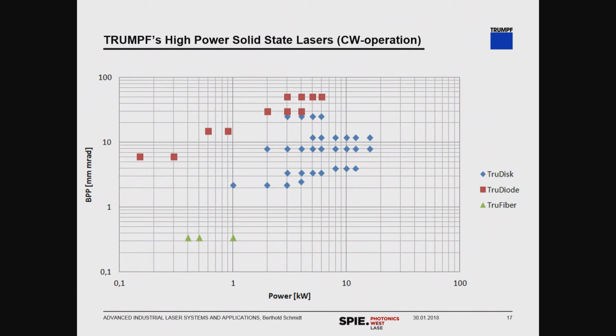Then we have even higher power disc lasers. And then you see here our conventional direct diode laser systems that range from brightness levels of 30 to 50 millirad. Naturally, there is an activity going towards bringing those down. But first, let us look at the single mode or single disc achievements we have already published. There was a very interesting paper 2 years ago from our team in Schramberg that showed an almost single mode disc at 4 kilowatt that was pumped with 969 nanometer into the zero phonon line.